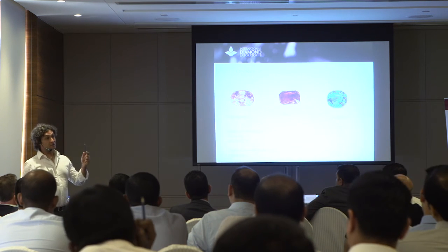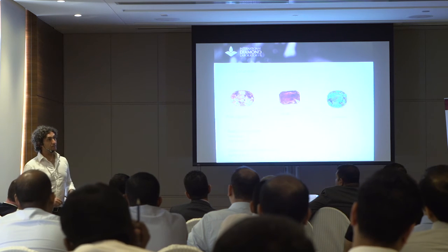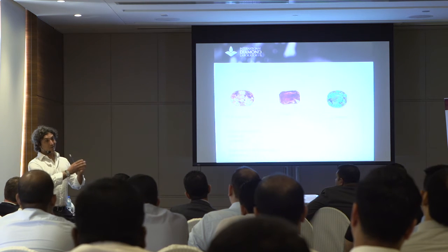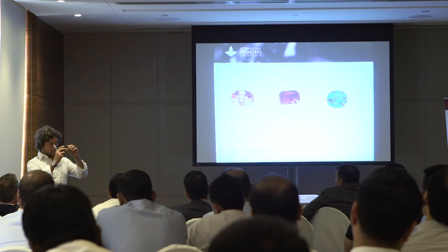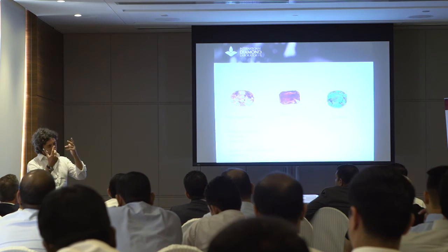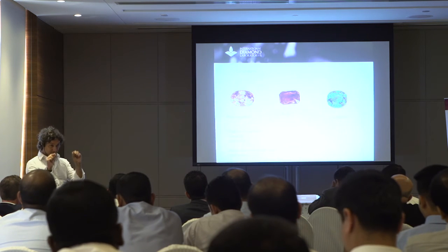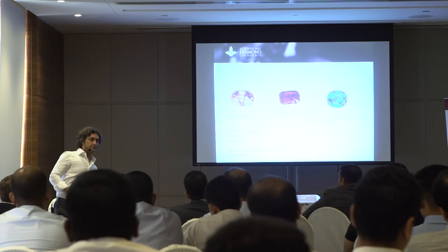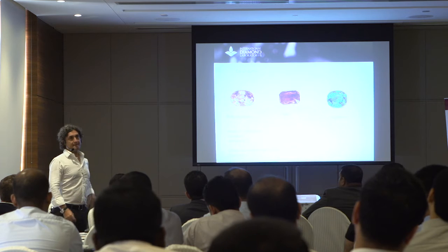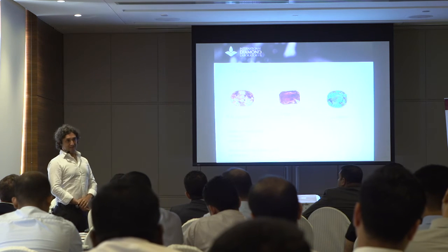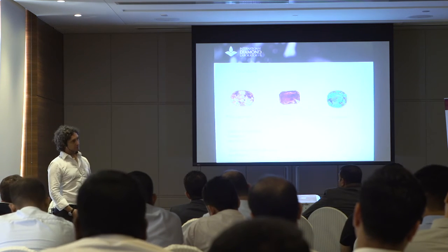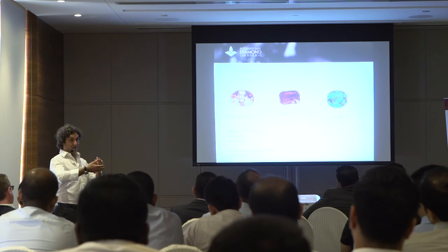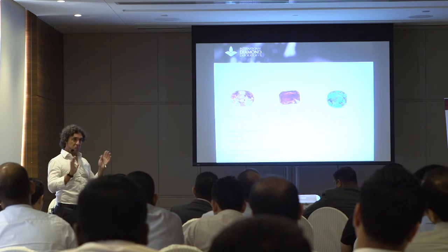Then we have diffusion treatment. Diffusion treatment is a thermal process plus some chemical that will diffuse, penetrate a very thin layer of the stone. The regular blue diffused sapphires are treated with titanium. So you do a thermal process, somehow you add titanium, it will go in, titanium will react and produce the blue. Then you have a blue sapphire.